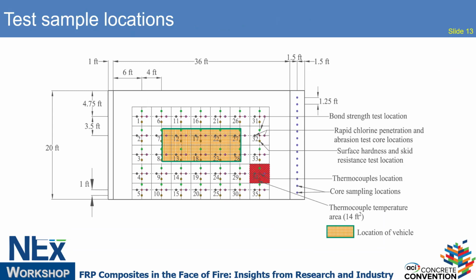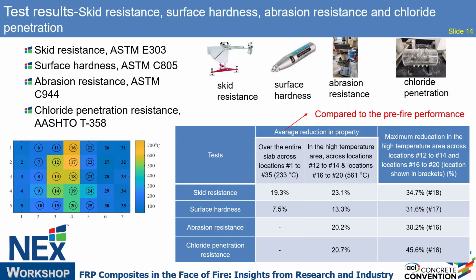So after the vehicle fire test, we collected samples from almost the whole slab surface to do post-fire performance tests to measure bond strength, rapid chloride penetration resistance, and surface hardness. We also measured delamination with the IR camera. So those are the results about the skid resistance, surface hardness, abrasion resistance, and chloride penetration.